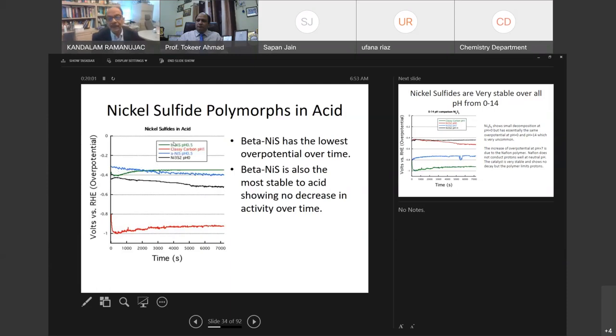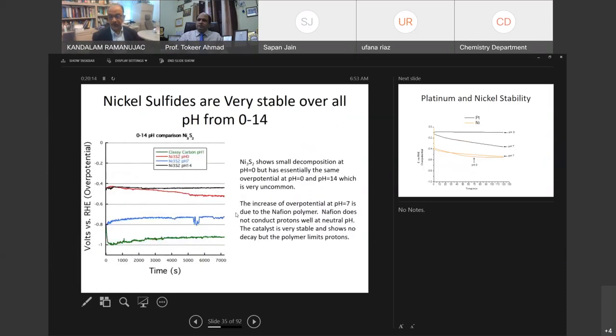But the best one is the beta form of the nickel sulfide, which is better than molybdenum disulfide, better than any of the thiospinels. So we were very excited. Great. So then we started looking at how stable are these materials under pH. So we have studied pH 0, pH 7, and pH 14 of all the samples. As you can see, at pH 7, the performance is not very good in the neutral pH. Then we started looking at why is this.